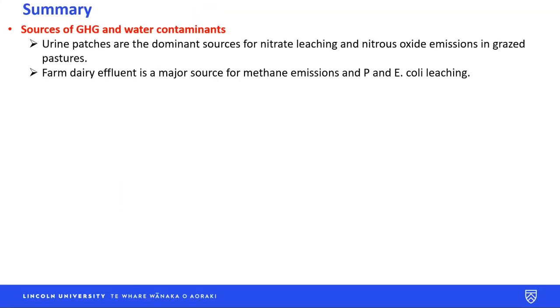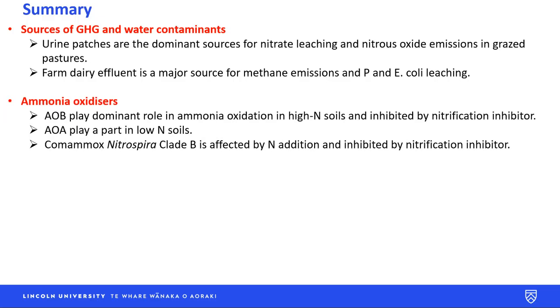So just in summary, we quantified the sources for nitrous oxide and nitrate leaching. Urine patches are the dominant sources, and effluent can be a major contributor for phosphate and E. coli leaching. We looked into the ammonia oxidizers and found that bacteria are the dominant community responsible for ammonia oxidation in the urine patches. Archaea don't do much. And then comammox is also there, and they play a part, but they can all be inhibited by nitrification inhibitors.